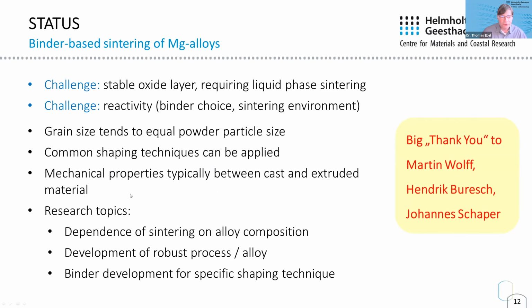So the research topics we are working on now are to understand the dependence of the sintering on alloy composition, because what we observe is that we have some alloys which sinter very nicely, others are a little bit different. In many cases we have alloys with a porosity after sintering between 1% and 2%. That's really low. So it is sintering, but it depends on the process and on the alloy.